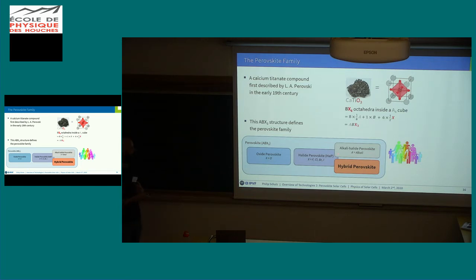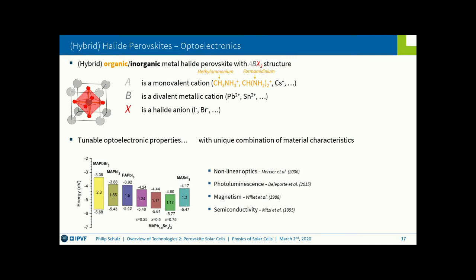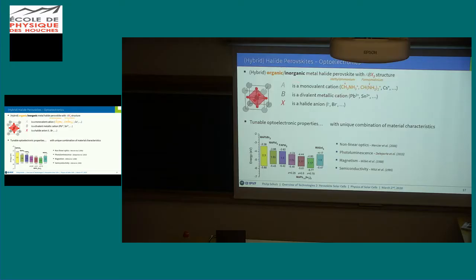And here we differentiate between alkali halide perovskites. I think it's wrong in your slides because I still wrote that the alkali should be on the B side. It's actually on the A side. And then also the hybrid perovskite, where the A side can be occupied by an organic molecule. We come to this on the next slide, where the hybrid organic inorganic perovskite, you have on the A side a monovalent cation, which can be an alkali metal like cesium, but it can also be an organic molecule, small molecule like methylammonium or formamidinium. This one, methylammonium, or MA in short, was really the prototypical perovskite that led to the breakthrough, whereas formamidinium-based perovskite ink formulations make currently the highest performant, and also most stable devices.